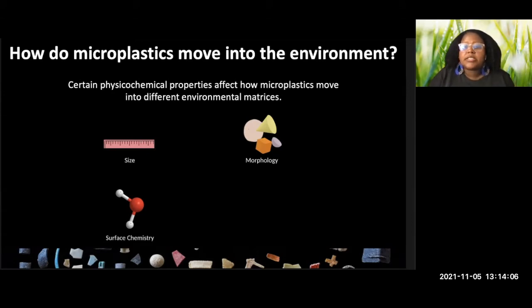Degradation processes such as photooxidation can create new functional groups by way of photogenerated radicals, which result in the embrittlement of the plastic surface, so cracking on the plastic surface, and as a result, further fragmentation. This results in smaller microplastics being produced, and therefore a higher surface area to volume ratio, allowing for absorption of different biota and contaminants. So surface chemistry really does influence where specifically these microplastics end up, because it can in turn alter the density of the microplastic and may result in sinking and or suspension dependent on the density profile at depth.